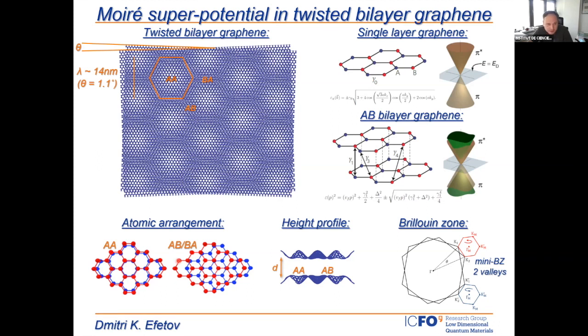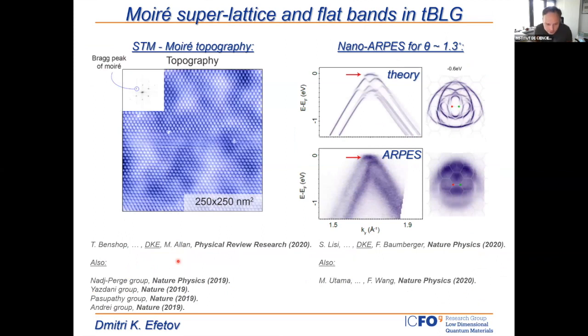And just to give some early experimental indications of the system as such. First of all, these moiré lattices are robust, so we can image them with scanning probe techniques. For example, this is an image done by our collaborators Milan Allan in Leiden, and they were able to image with STM and resolve a really periodic moiré superpotential. So all of these periodic dots which you see are not single atoms, but those are really these moiré lattice sites.